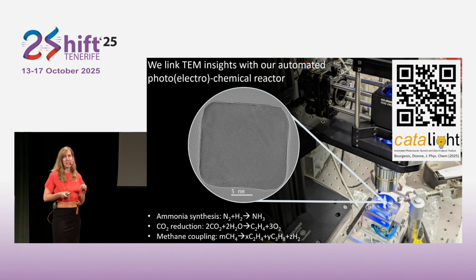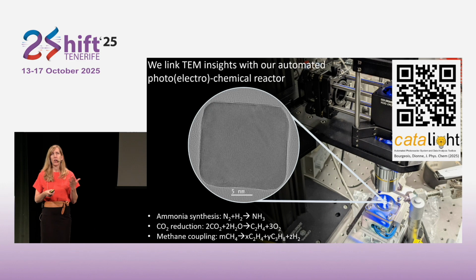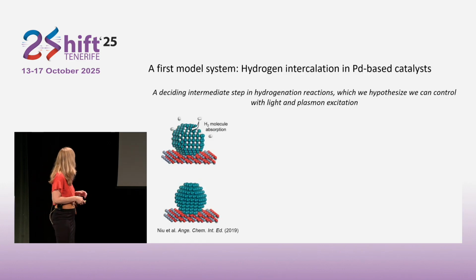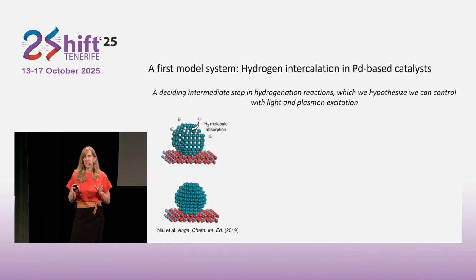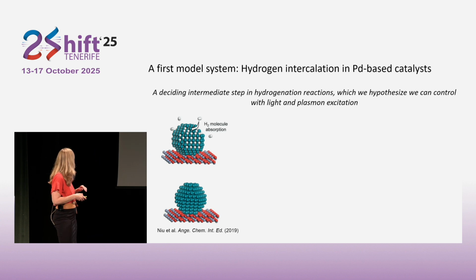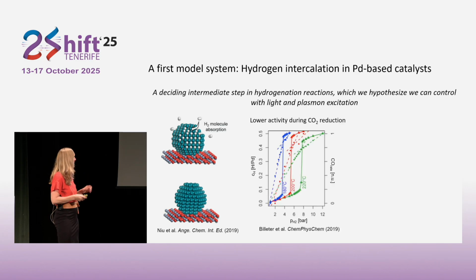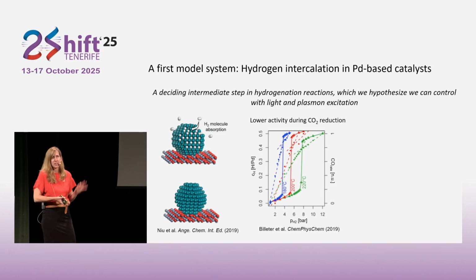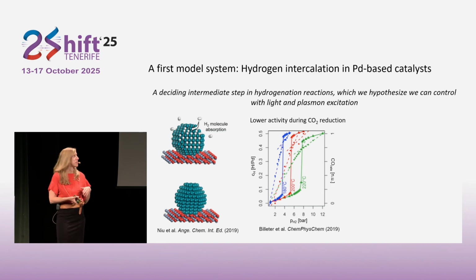So when we were first thinking about how to link basically the atomic scale to the reactor scale, we looked at these hydrogen-based reactions. And that's because hydrogen intercalation at the surface and subsurface of these nanoparticles is a really important deciding intermediate step in a lot of these critical reactions. And just to show a few examples, basically if you have hydrogen, H2, it catalytically splits at the surface of your metal nanoparticle. And depending upon how much hydrogen gets into the surface and into the subsurface of your catalyst, you can strongly influence the outcome of your reaction.